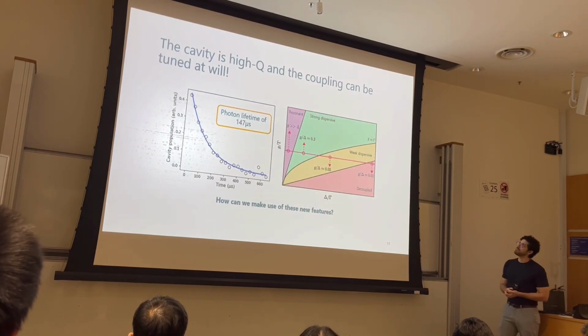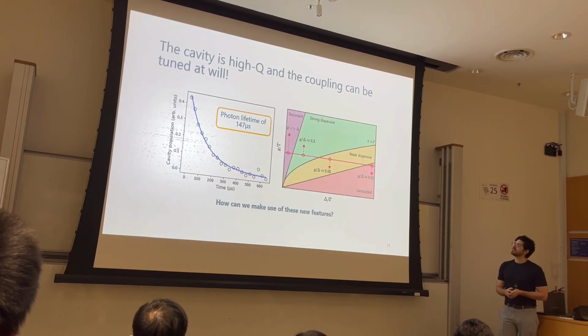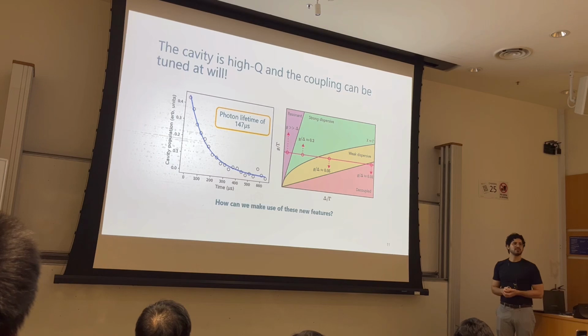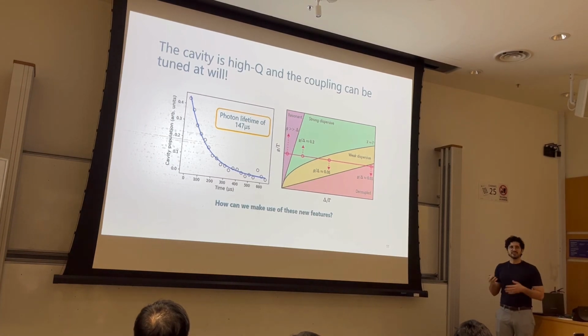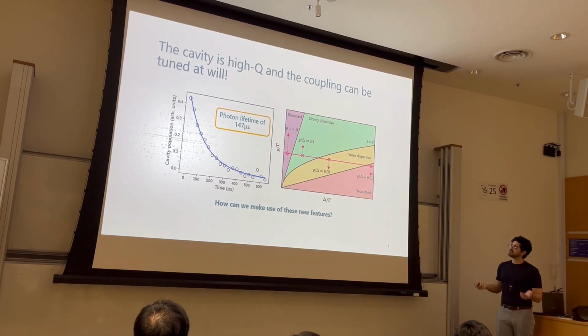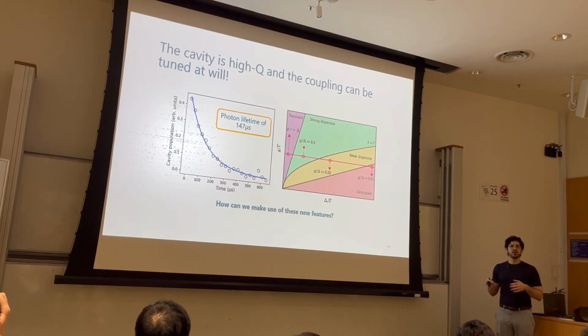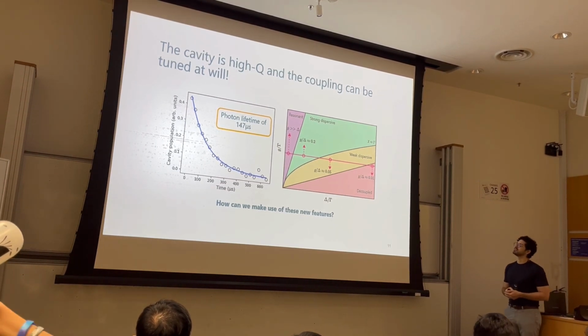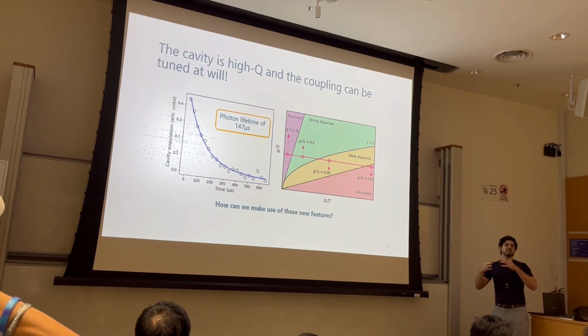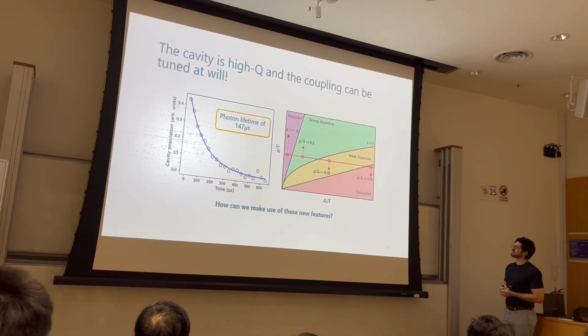And more importantly, we measured the cavity lifetime, and we found that its lifetime is roughly 150 microseconds. There was some variation from cooldown to cooldown. We sometimes got even higher lifetimes, but this value is already very good for a good chunk of protocols in quantum information processing. So we had overcome that barrier from the previous experiments.